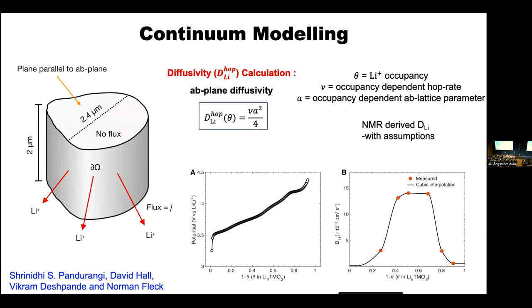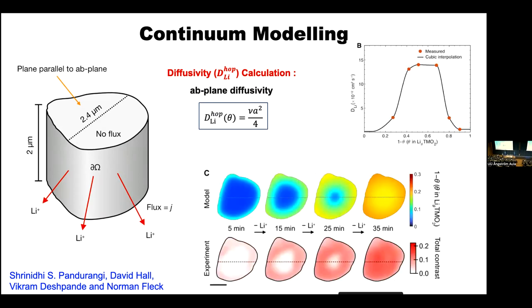Okay, so then to try and understand this and pull out more information, I turned to collaborations with my colleagues Norman Fleck and Vikram Deshpande, who are continuum modelers and mechanical modelers too. The postdoc Shri developed a model of our particles. To put into the continuum modeling, he took the chemical potential from the voltage capacity curves, and then he took the lithium conductivity from the NMR spectra, converting that into hopping frequencies. He took the most optimistic, the fastest hopping that we had extracted from NMR, and developed this model where he could beautifully simulate this core-shell type behavior that we'd seen experimentally.